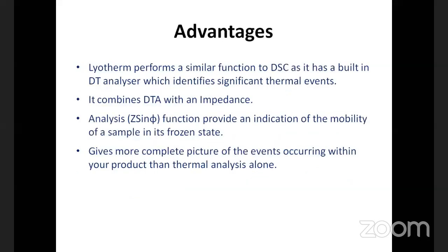Advantages include we can perform functions similar to that of DSC, as it has an inbuilt differential thermal analyzer which identifies significant thermal events. As I mentioned earlier, it is integrated equipment of electrical impedance as well as differential thermal analysis. So it combines DTA with impedance analysis. This Z sin phi provides information about mobility of the sample in its frozen state, and it gives a more complete picture of events at different temperatures occurring within the product than thermal analysis. So compared to DSC, this particular integrated combination is a perfect fit to determine the exact collapse temperature using a very small amount of sample and in a short time.